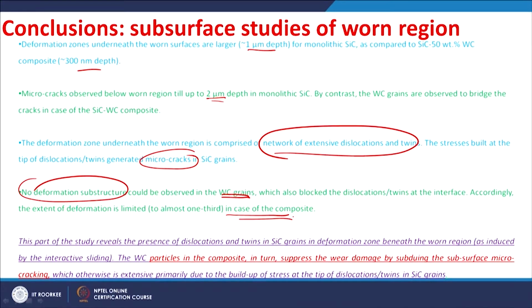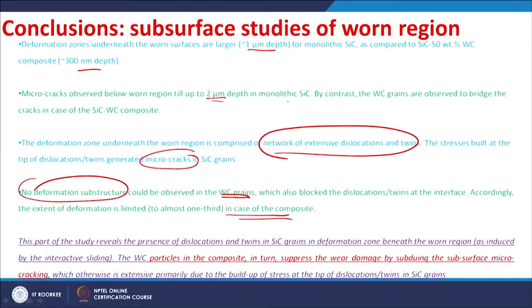So, this particular study is very important in the sense that for preparation of such a sample for TEM analysis, the sample must be taken from the region underneath the worn surface. So, for that FIB was used and then TEM analysis was done carefully, which revealed this information about the deformation zones, the cracking as well as the beneficial effect of the tungsten carbide particles in the silicon carbide ceramics.